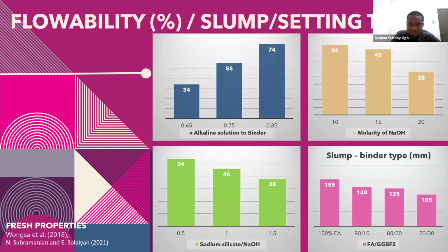So the workability is high because if you remember, the chemical composition of fly ash has a very small percentage of calcium oxide. So because of that, it takes longer to set. So that's the major reason why you see the workability is high. However, when you introduce the slag into your binder, it means you're increasing the calcium oxide content in the binder because GGBS has a higher percentage of calcium oxide. So that is the major thing that reduces the workability because it sets very fast. So as you mix, it accelerates the solidification. Geopolymerization begins to take place instantly.